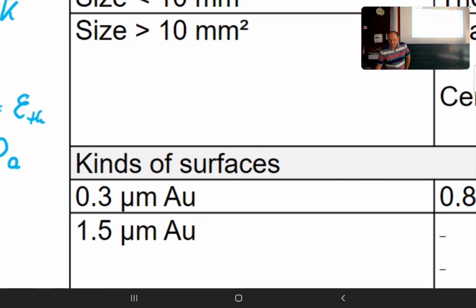The second reason is lead frames. Nowadays, we mostly use copper. And for copper, the CTE difference would be really high. Yes, it would be a factor of 10 higher. And then 1000 megapascal is, of course, out of range. But for wafer bonding, it's not a problem because the wafers we bond together have the same CTE. So the delta alpha is more or less 0.